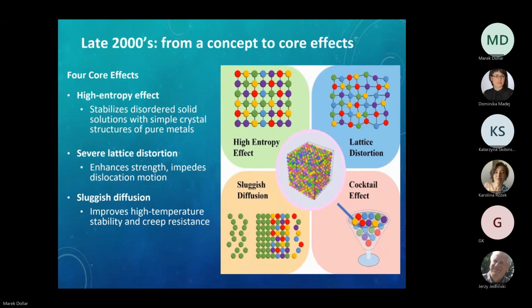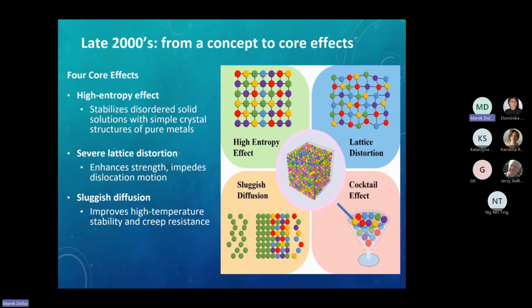Sluggish diffusion. Because of different sizes, vacancies, or atoms, you can use the terminology in parallel, move much slower than in conventional alloys. And this is huge because creep is the biggest concern for high temperature applications, it is the creep resistance of the alloys. And the sluggish diffusion contributes to this. Cocktail effect. There are some first studies related to this effect, but the point is a kind of non-linear enhancement of properties.